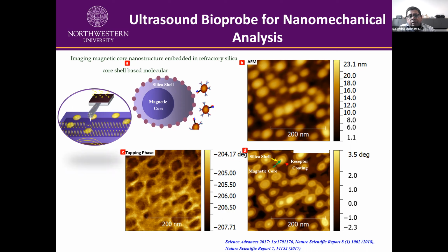And then the bottom left is basically the conventional tapping mode image, where you can see different contrasts based on the surface elastic properties. But the bottom right is the ultrasonic image, where you can see the embedded magnetic particle, the contrast coming from the magnetic particles in the silica core. So you can clearly see those magnetic particles embedded in the silica with this ultrasound holography. So that basically allows you to image subsurface structures. So basically, if somebody wants to track nanoparticles within the cellular network, you can do that. You can image those nanoparticles within those networks, and we have seen those things.